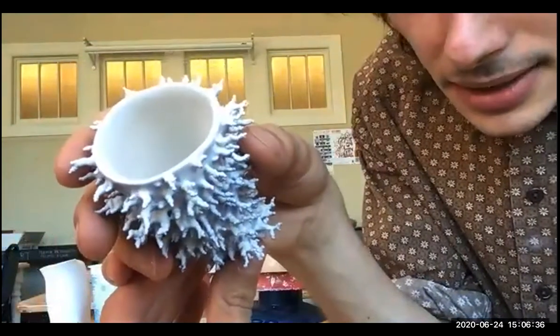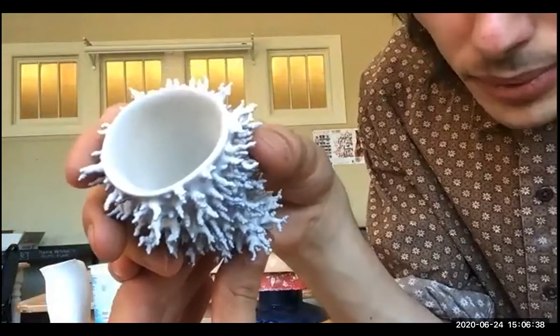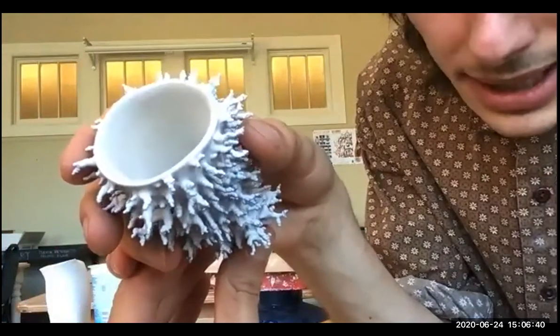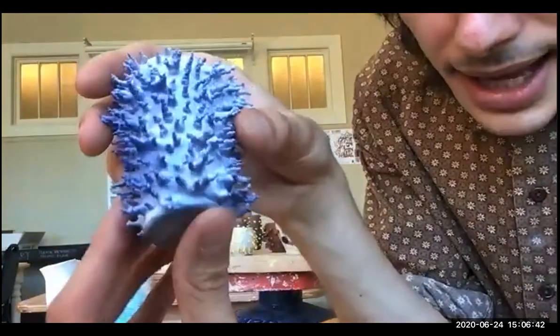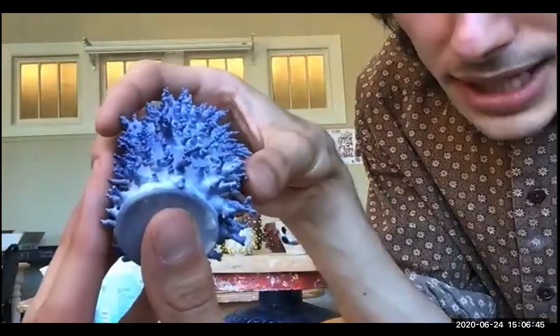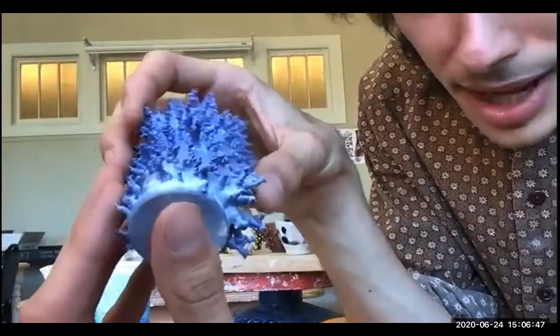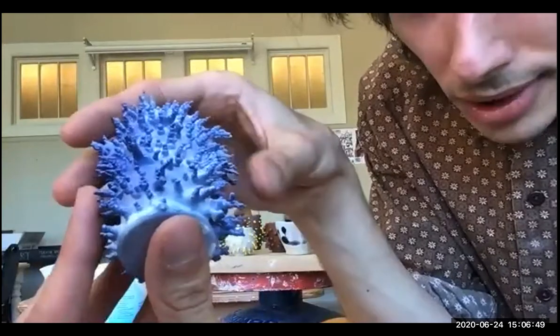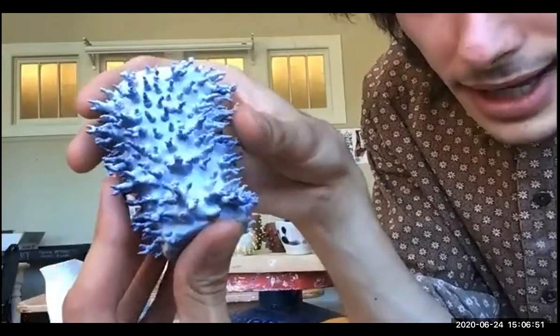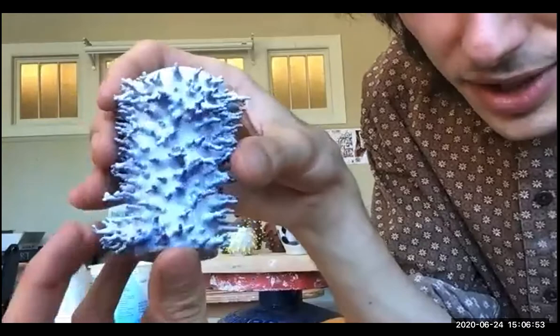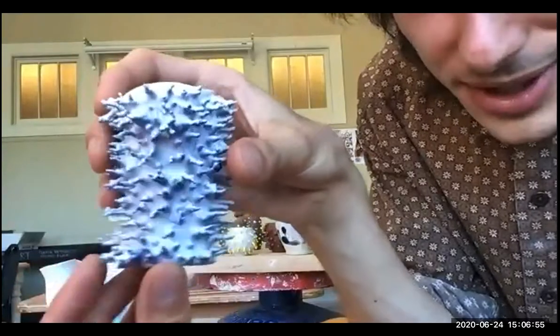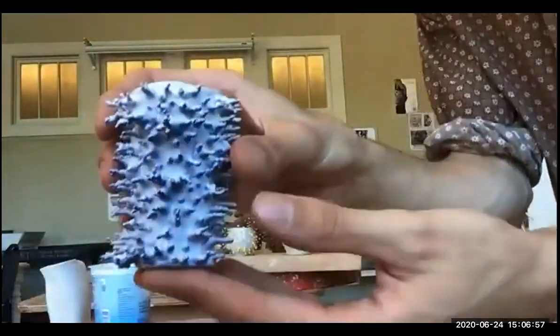And this is on basically a white slip with a porcelain clay body and a glossy white glaze. And then I spray it from underneath with a blue china paint, basically a cobalt and lead that's fired at about 1300 degrees. So the blue doesn't disrupt the glaze once it's fired another time.